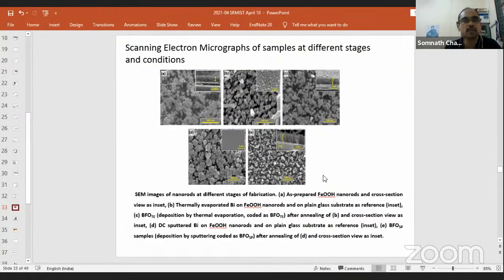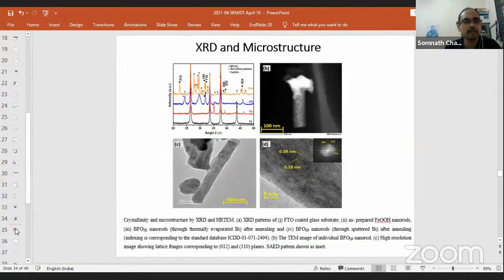But there are two issues here. My next student is now working to resolve them. As you can see on this screen, the nanorods are there, and the XRD. There are two issues. One, we still have some secondary phase of bismuth, the Bi2Fe4O9 phase. And then the nanorods are still not very long. We could get nanorods of around 1.5 micron only. Unlike the TiO2 nanotubes, where we had around 5-6 micron, we are trying to get this.